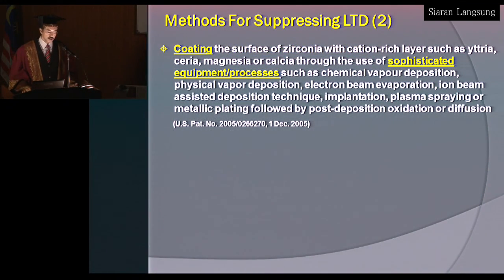The other method is to coat the surface of zirconia in order to interrupt the reaction between hydroxyl and Zr. This is done by using sophisticated equipment and processes such as chemical vapor deposition, physical vapor deposition, electron beam evaporation, and so on. These are expensive techniques. Basically, we coat the surface with a layer of another material in order to prevent hydroxyl from reacting or coming in contact with the tetragonal structure.